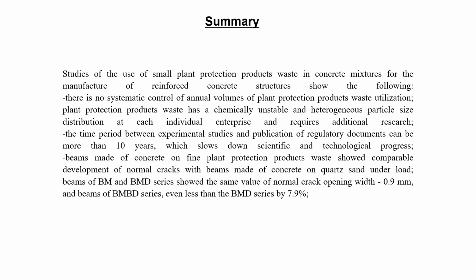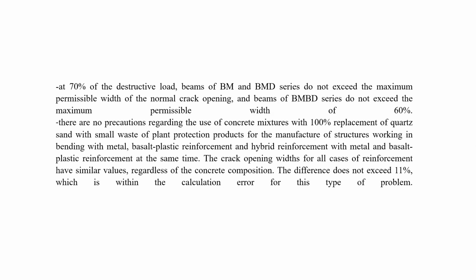Beams of BM and BMD series showed the same width value, 0.9 mm, and beams of BMBD series, even less than the BMD series by 7.9%. At 70% of the destructive load, beams of BM and BMD series do not exceed the maximum permissible width of the normal crack opening, and beams of BMBD series do not exceed the maximum permissible width at 60%.